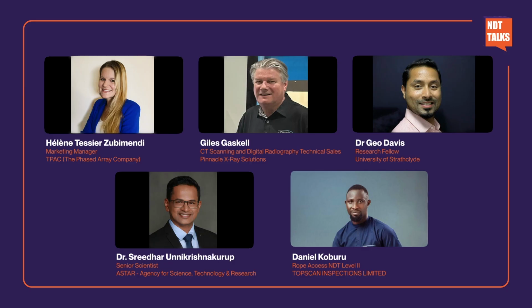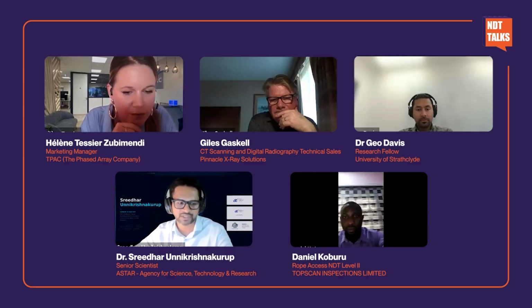Thank you. Yeah, so you already talked about X-ray CT and also ultrasonic techniques. Maybe I can say a bit more about thermography. Thermography is considered an emerging technique. It is not traditionally well used in NDT inspection methods. But in thermography itself, there are different ways of inspecting additive manufacturing components. Traditionally, the method we used is the flash method, which uses optical excitation with a pulsed flashlight. And then there is lock-in inspection, in which you excite the sample using a periodic excitation.